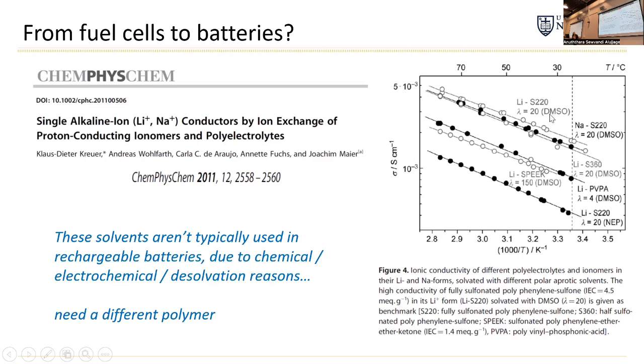Here they use dimethyl sulfoxide. DMSO is an excellent cation solvator, but it's not chemically stable against lithium metal. It reacts with it instantaneously, it has really limited electrochemical stability, and it also has trouble desolvating the cation at the electrochemical interface. The reason they use these solvents is that without these so-called excellent solvents that are not typically used in batteries, the conductivity is still too low. So we really need a different sort of polymer.